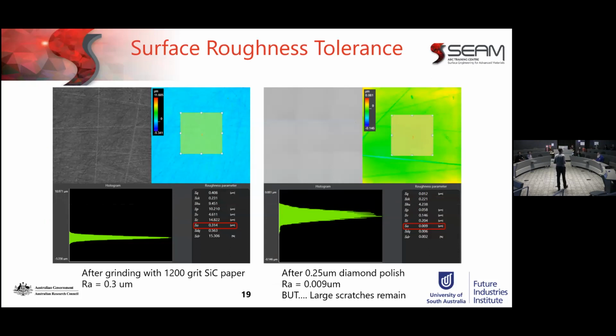But surface roughness, talking about what we can achieve: just grinding it, we're at 0.3 microns, but once we get to our polish, we're into the 9 nanometers. On the small scale, that's good enough for us, but you can see up there we've still got some large structures in the polish, which isn't quite acceptable.